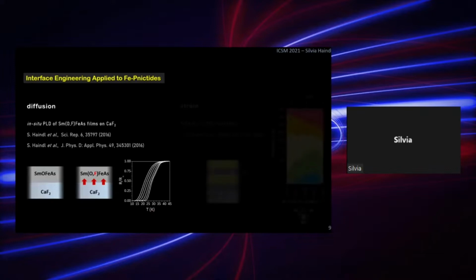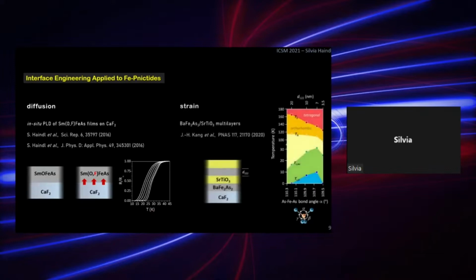Another approach has been adopted by Iida's group, the so-called strain engineering, and here barium iron 2 arsenic 2 STO multilayers have been grown with different thicknesses, and what you can see on the right side in the phase diagram is when you decrease the thickness of the barium 122 layer, you can change and tune the arsenic-iron-arsenic bond angle, and by that you can change the electronic state and induce superconductivity. However, both approaches have not focused on the fundamental aspects of the iron-pnictide heterointerfaces, and this is now done by this new classification which we have proposed recently in NPG Asia Materials.